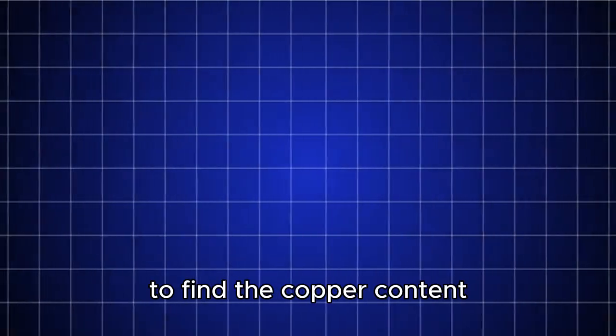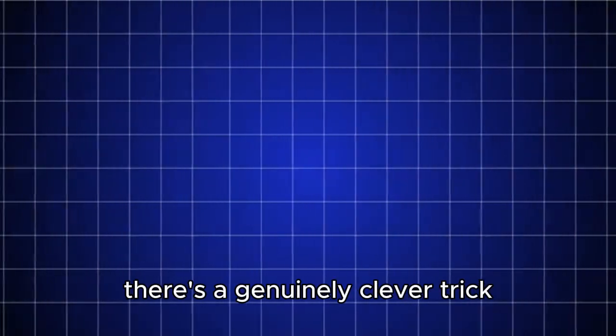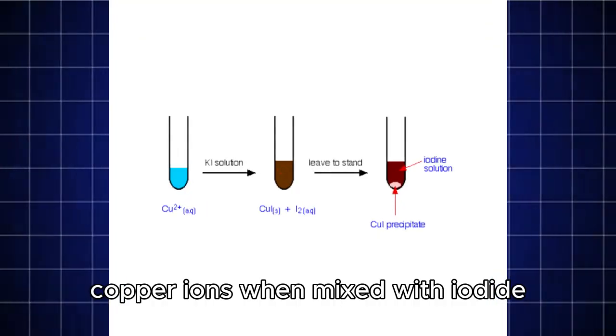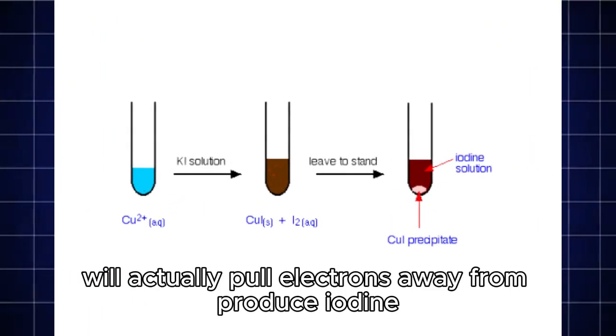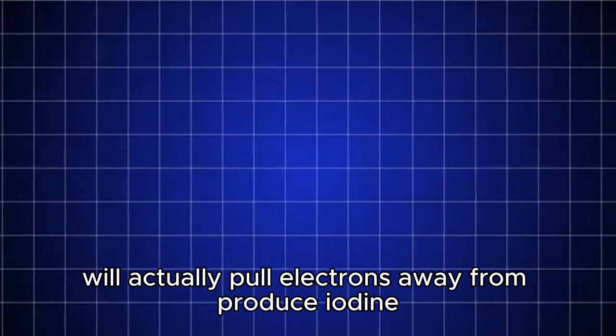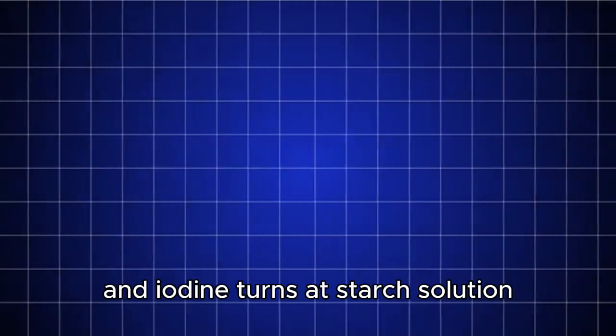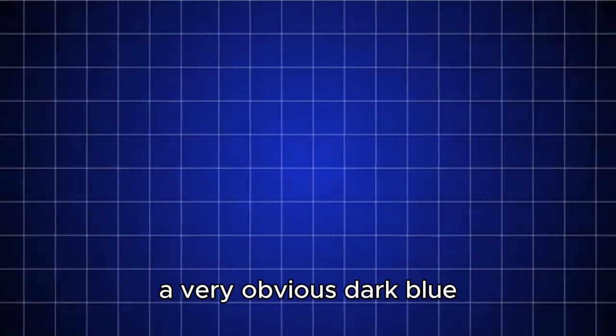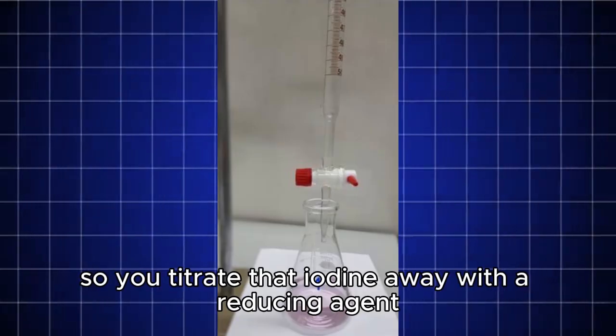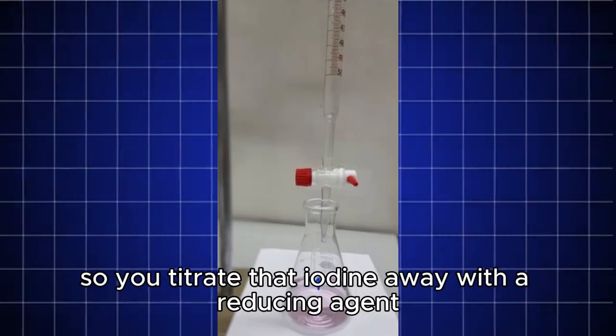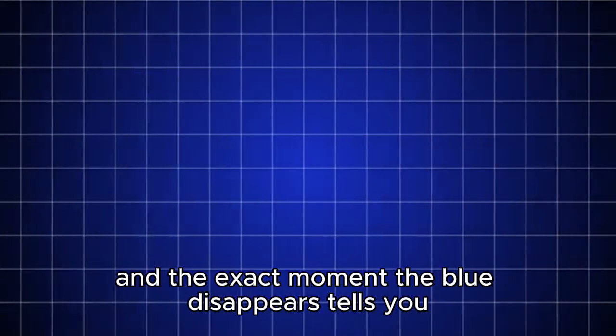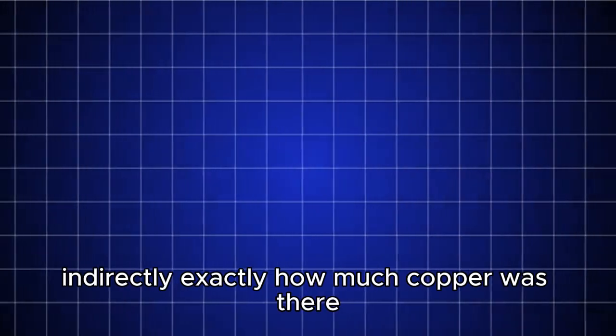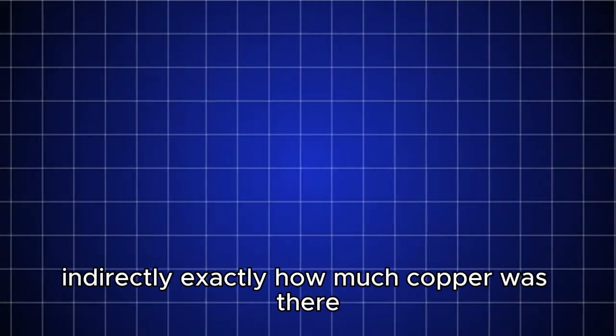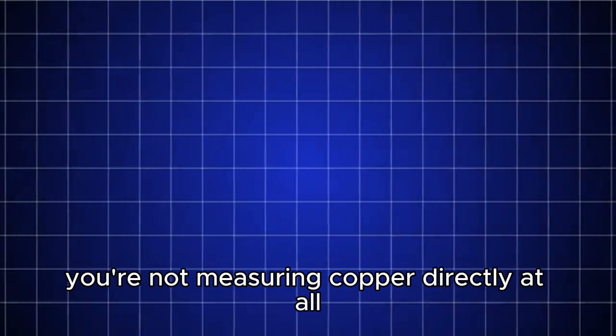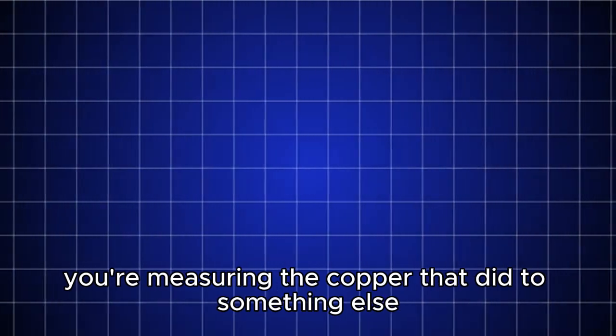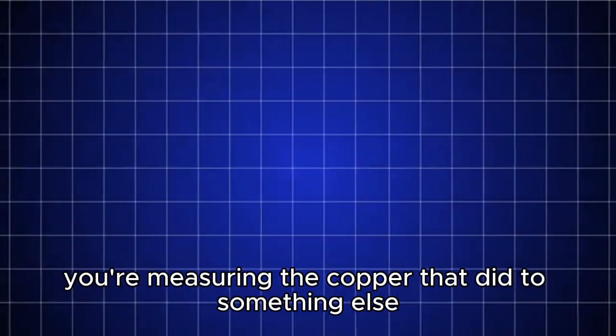To find the copper content, there's a genuinely clever trick. Copper ions, when mixed with iodide, will actually pull electrons away from iodide, producing iodine, and iodine turns a starch solution a very obvious dark blue. So you titrate that iodine away with a reducing agent, and the exact moment the blue disappears tells you indirectly exactly how much copper was there. You're not measuring copper directly at all. You're measuring what the copper did to something else.